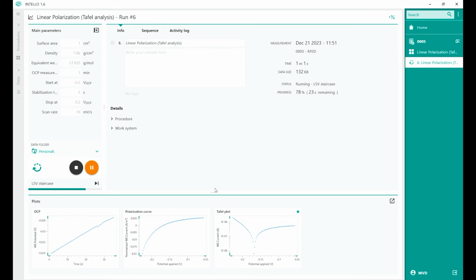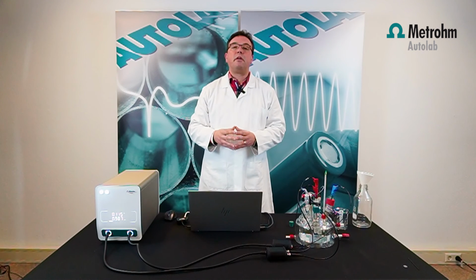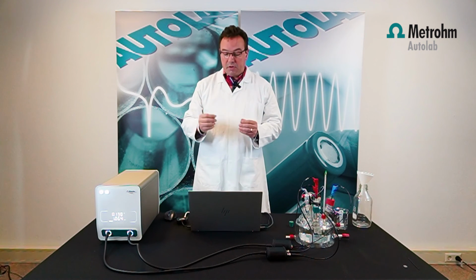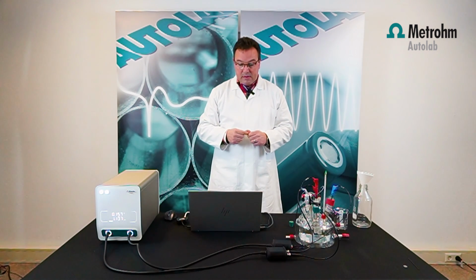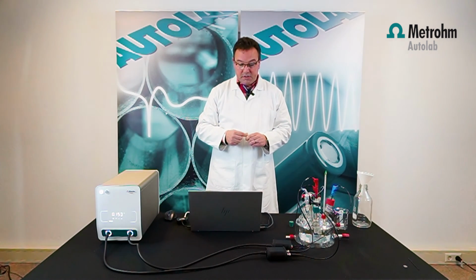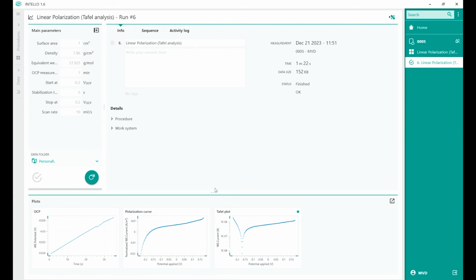In order to perform the corrosion rate analysis, the linear regression of the anodic and the cathodic side of the Tafel plot must be specified. This is accomplished with the help of 4 markers, 2 on the anodic side and 2 on the cathodic side. And such markers define the lines for the linear regression according to the Tafel equations. So the measurement is almost finished. So the measurement is finished.